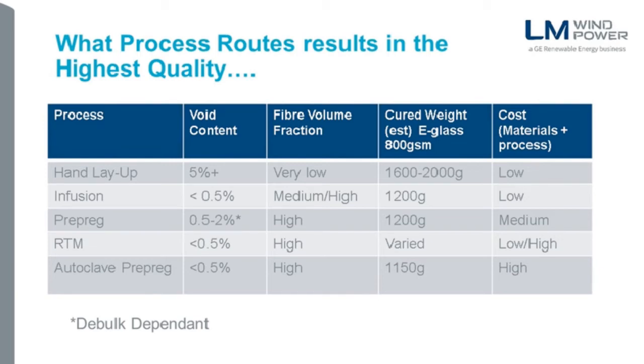So we can see this slide. The interesting bit for me here is that the numbers on infusion look very close to prepreg and autoclave prepreg, except for the cost. And this is why I think infusion is certainly for the industry I'm in, for wind turbines, the trend recently-ish has been to move to resin infusion because you get this nice low void content, you get high fiber volume fraction, low cured ply weight for low cost and without the need for prepreg and the freezers and the curing oven and the heated tools.